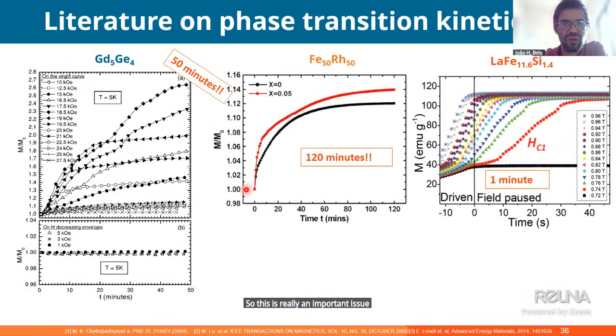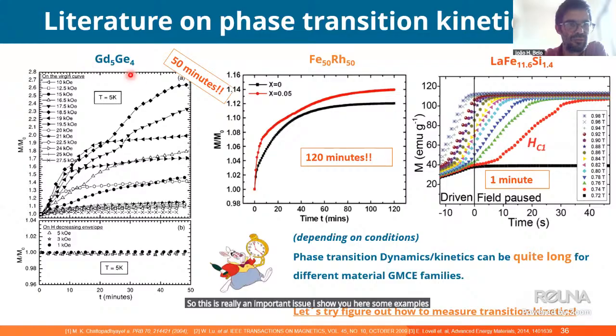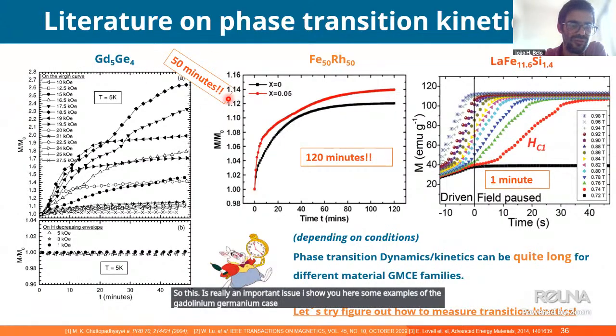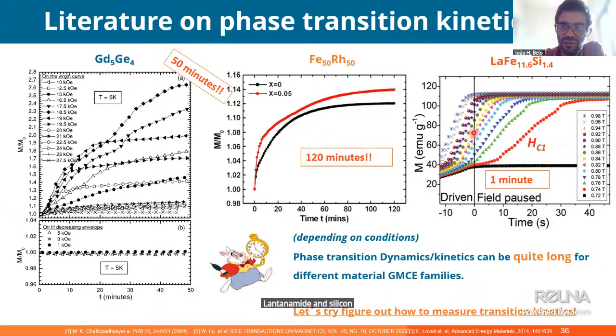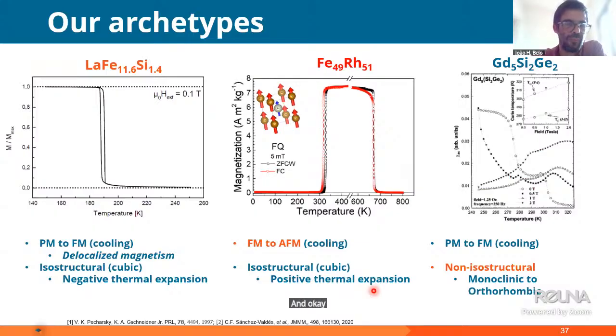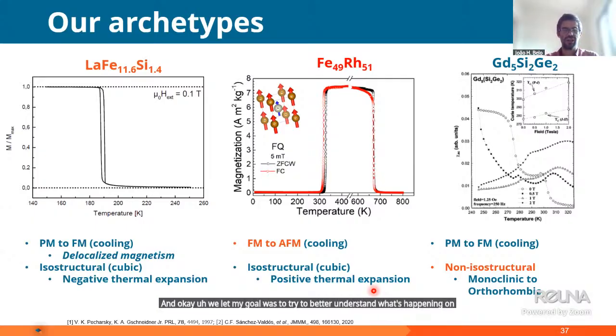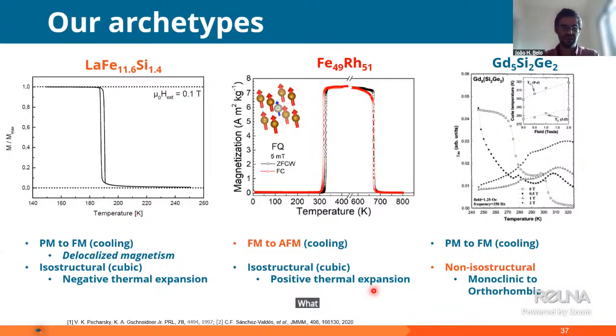I show you here some examples of the gadolinium germanium case where in specific conditions the transition can take up to 50 minutes. Iron rhodium, it can take up to a few minutes. Lanthanum iron silicon, again, a few minutes to some seconds. So this phase transition can be quite long. And my goal was to try to better understand what's happening in this phase transition kinetics. So what is taking these materials so long to respond to the stimulus?